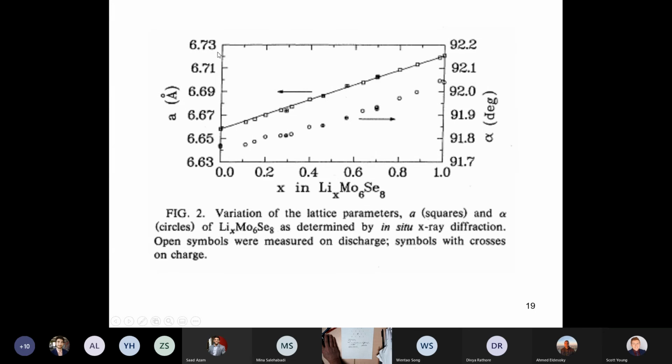This shows you the lattice constant. So again, it's basically a simple cube that the lithium atoms sit on. It's not quite a perfect cube. A perfect cube would have a rhombohedral angle of 90 degrees, but you can see it's close to 90. And sure enough, the lattice expands as you put the lithium in. So because of that, the lithium prefers to be close together, but the expansion's not enormously huge. So the strain-mediated attractive interaction is relatively small, and it's negative, it's attractive.